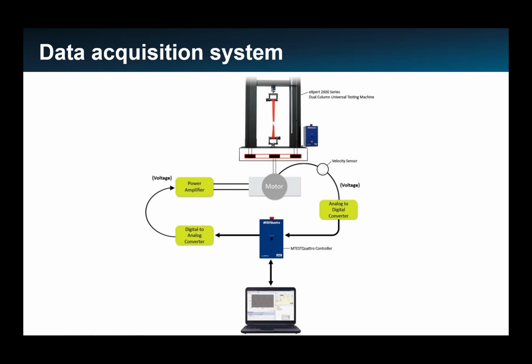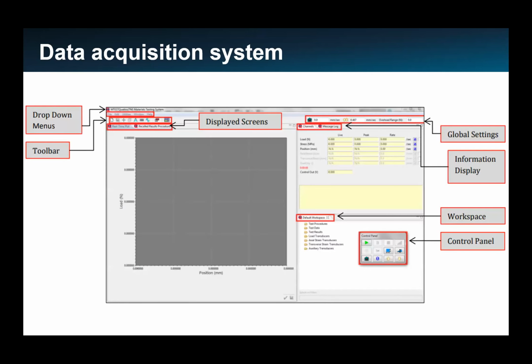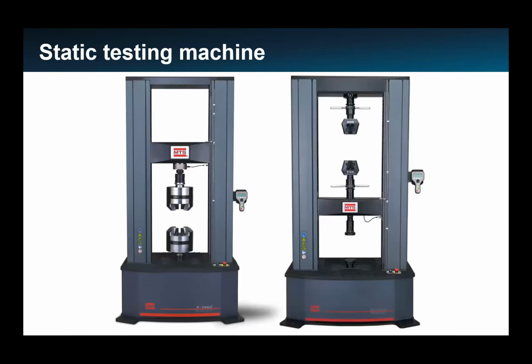So the software can display the load displacement curve in real time and calculate the material properties such as stress, strain, modulus of elasticity, and ultimate tensile strength. This is how the software looks. And as mentioned before, this software collects the data and analyzes the results. So this is a machine which is quite different from the one that we've shown before. The machine that we showed before can only measure up to 2,000 pounds, and this can actually measure up to 67,000 pounds. I would say that with the first machine we can calculate the results more precisely.